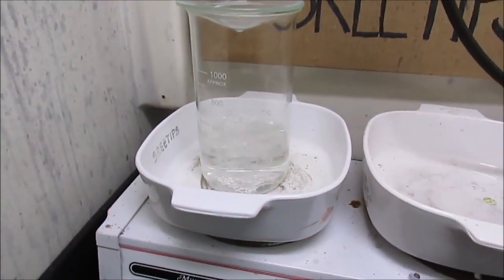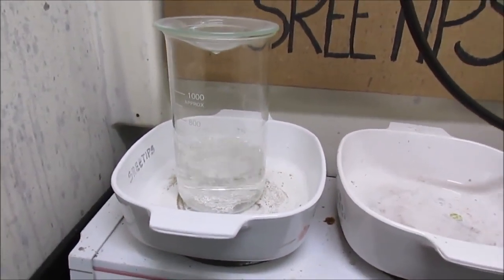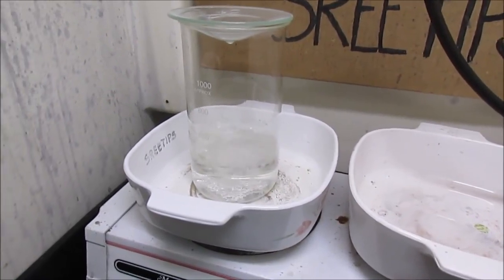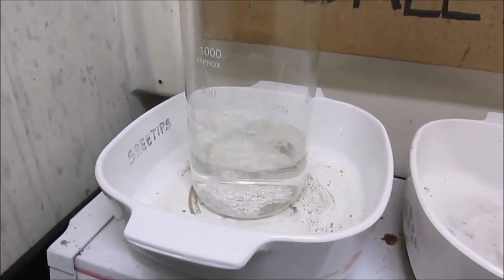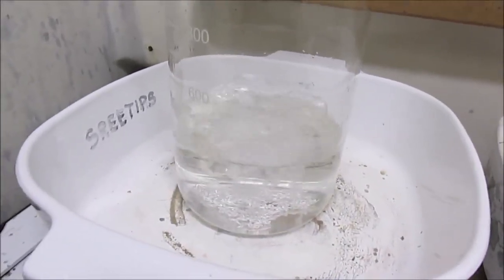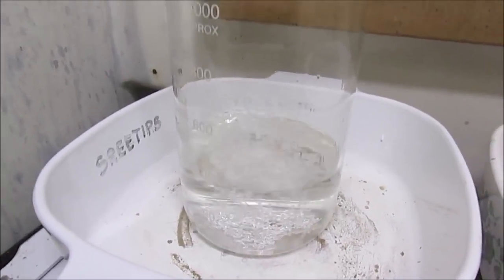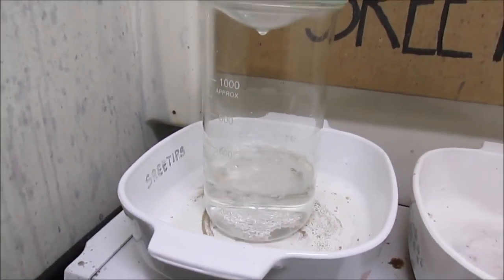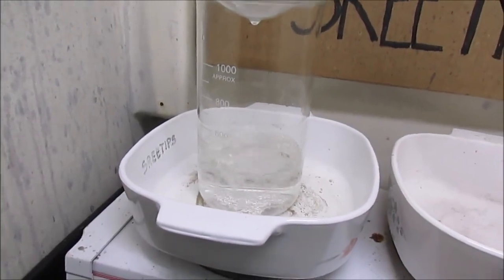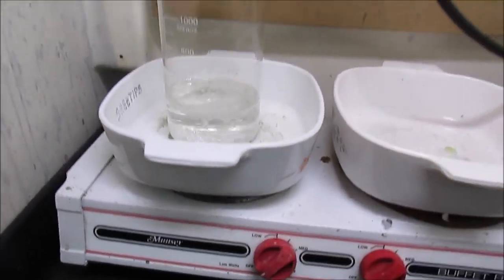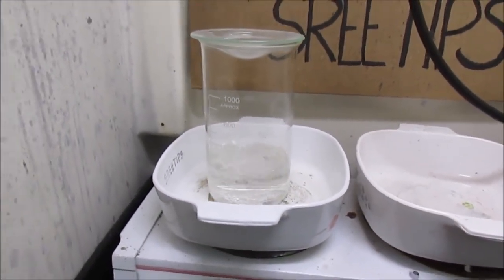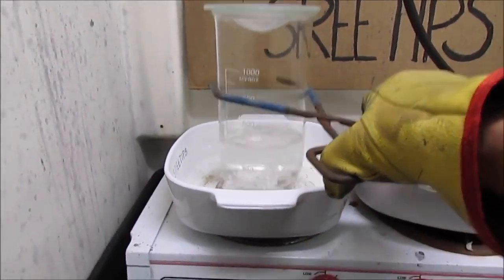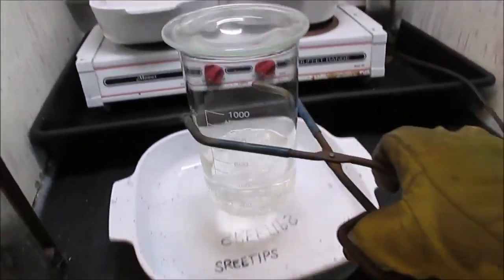The electrolyte has been on the heat there for about 4.5 hours. If you look down in there, you'll see that there's just a few grains of silver left over, no fumes. And so what we're going to do now is turn the power off. And I'm going to take this off the heater there, and we're going to let this cool down.